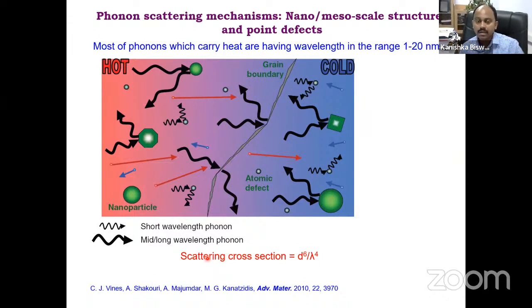high performance thermoelectric material. So in the 1950s and 60s, people tried to make solid solutions, like lead tin telluride or lead telluride selenide. So they dope selenium on the tellurium position, tin on the lead position, so that they create point defects, or atomic point defects, which are on a very, very short scale, the angstrom scale, which are not so important to scatter the important phonons, which are in the range of 1 to 20 nanometer. And they have also created grain boundaries, which are in the mesoscale, like micron scale, which also do not scatter the important phonons which carry the heat.